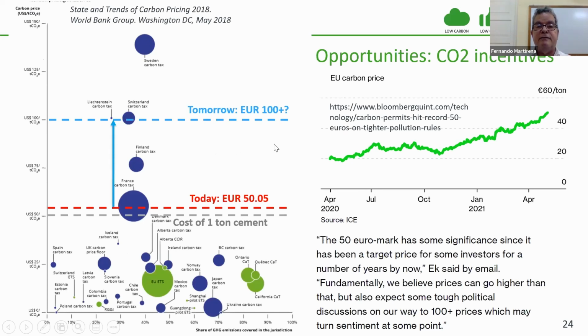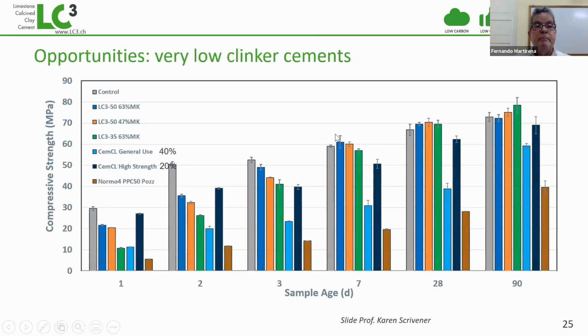So incentives associated with this could be a very good driver for introducing these kinds of cements in Africa, and you should bear this in mind. But there are also very interesting opportunities for cement producers, which is to produce very low clinker cements. Remember, concrete is only 40% of cement applications. The rest is masonry, finishing works, other works, and we can produce a cement that has only 35% of clinker.